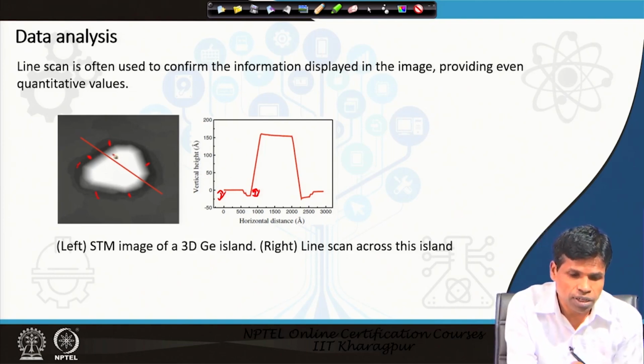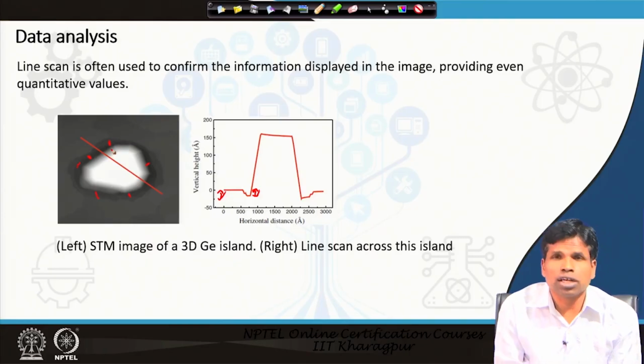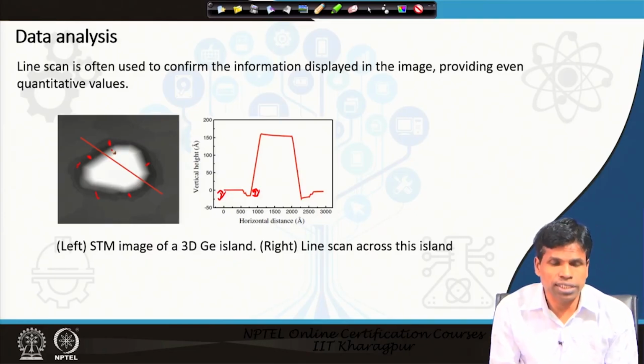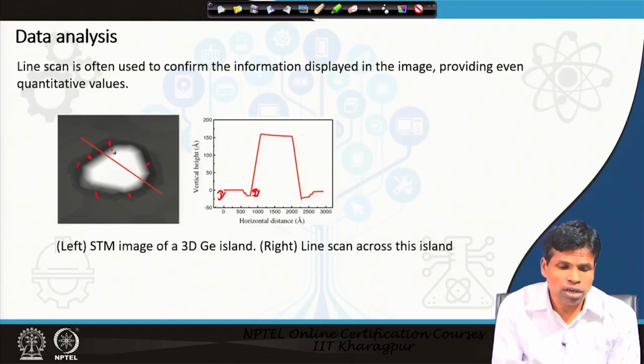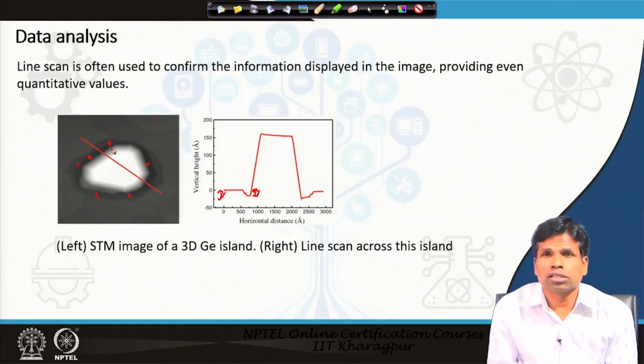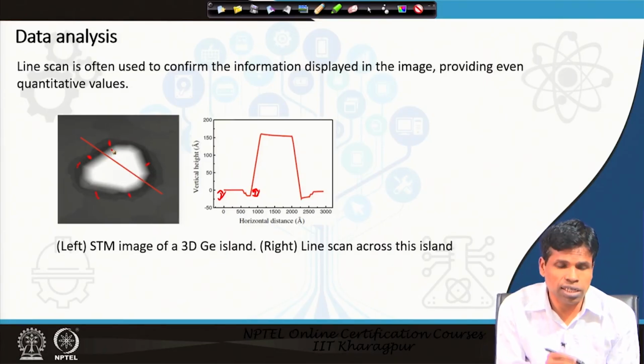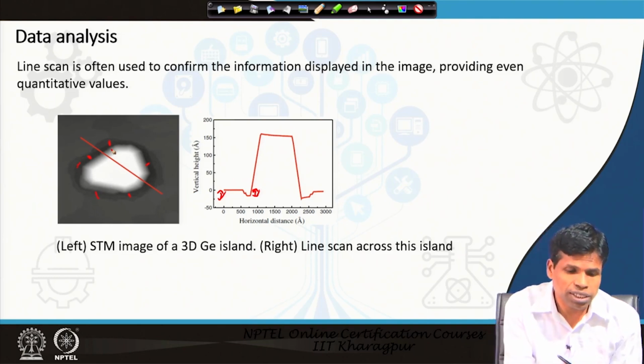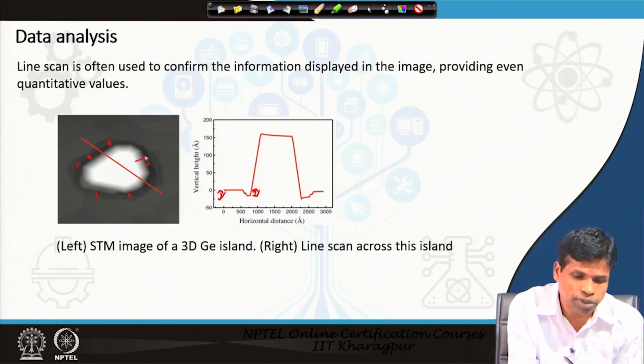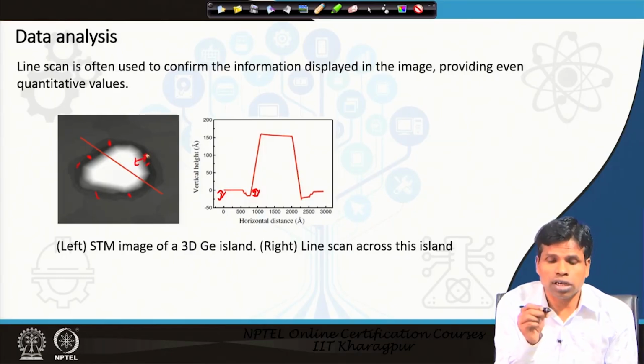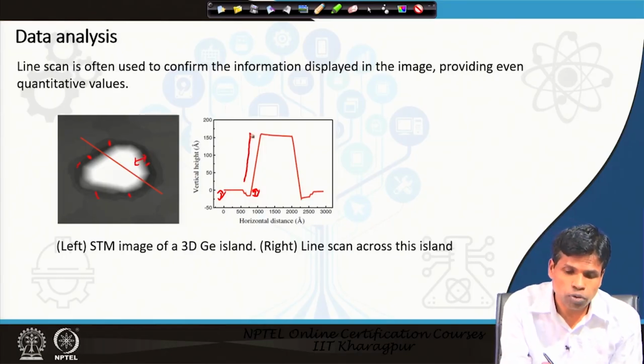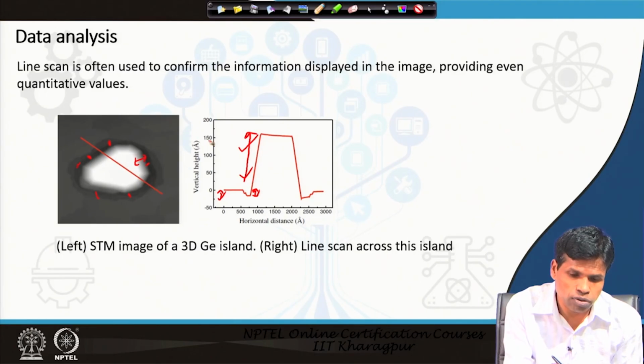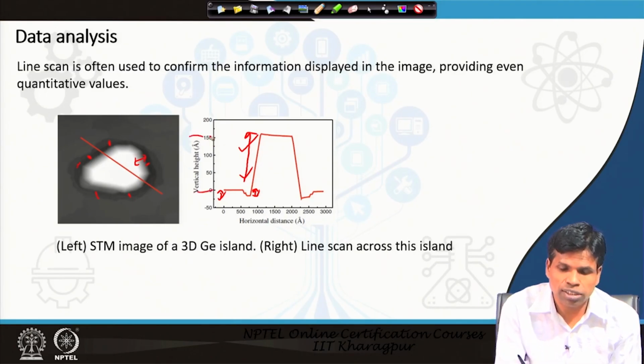And in addition to that, we certainly know it is a 3-dimensional image from other microscopic techniques such as SEM and helium ion microscope. In these cases also, from the brightness or darkness difference, we can certainly know it is a 3-dimensional image, but it is very difficult to make an accurate measurement of this height, how much above the surface. That we could do in these cases by measuring a line scan. Exactly, in this particular case, the height is around 0 to 150 angstrom, that is 15 nanometer. This quantitative value can